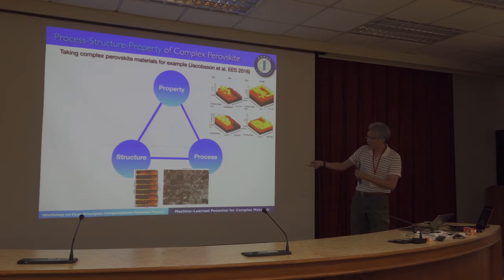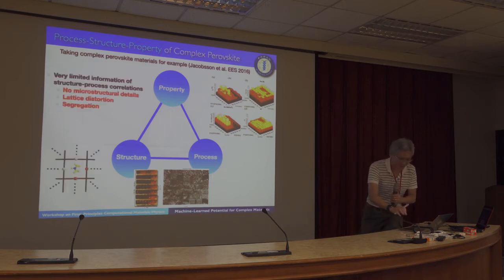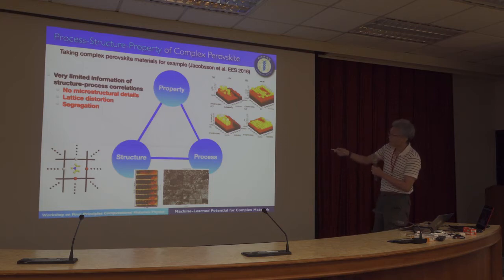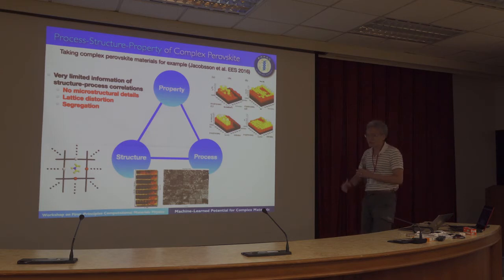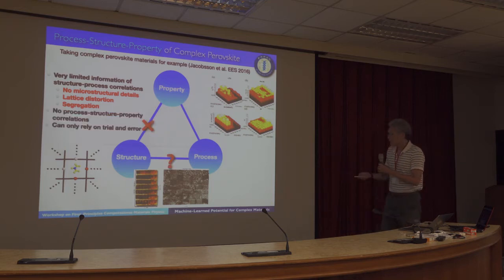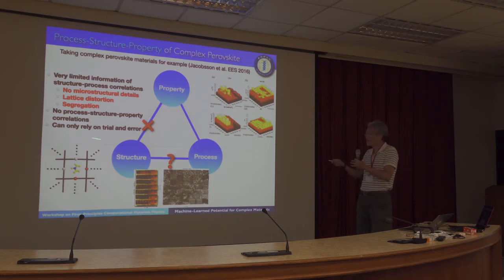However, for the structure, we only have SEM features and direct visualization, and we have very limited information here. We have no microstructure details. We have no idea about lattice distortion induced, because we know FA and MA and the bromine and iodine have different ionic size. And we have no idea if there's any phase segregation, domain boundary, whatever. And therefore that means that we cannot really construct the process-structure-property correlations. And therefore, for the poor students or poor postdoc, he can only rely on trial and error.